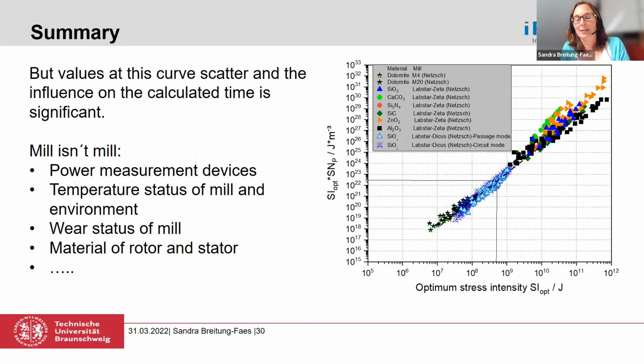And at least I would like to end my presentation with the hint to say a mill isn't a mill, because a mill which is maybe located here in Braunschweig may have the same geometry as a mill which is located somewhere else in the world, but as long as the power measurement devices are not the same, or the temperature status of mill and environment, or the wear status, or even the material of rotor and stator will influence your results. So it's hard to say I can predict results for a mill which is somewhere I never saw before.